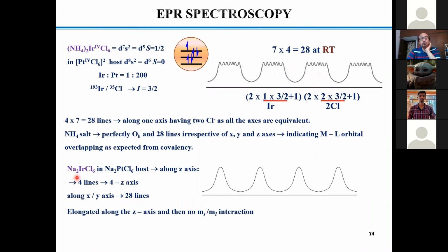But if you take the corresponding sodium salt, what do you see in X and Y axis? The EPR profile is exactly the way it is observed for the ammonium salt. But in the Z axis, you see no super hyperfine because of no MS and MI interaction for the chlorides. You only see the hyperfine 4 lines. Okay. What does it indicate? It indicates that it is not tetracoordination. It is essentially hexacoordination. But along the Z axis, the bond is slightly weaker, the distance is slightly longer compared to the X and Y axes. And as a result, it goes beyond the interacting mode. Interacting means MS and MI interacting mode.